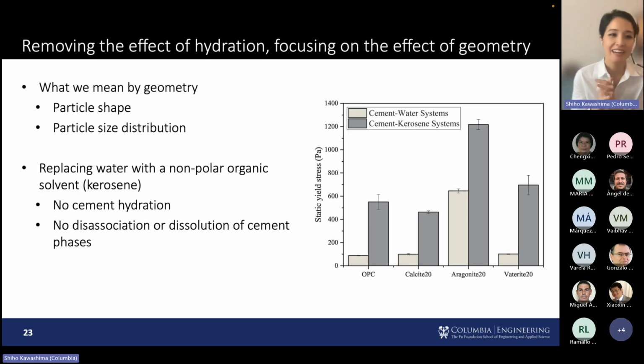And so to really isolate this effect and remove the effect of hydration, because I'm so sad to have missed Nicholas' talk, but I'm sure Professor Roussel emphasized that, the progression of hydration, even though we are in the dormant period or the induction period, it will have an impact on your fresh state properties, on rheology. So we want to eliminate that, and we did that by replacing water, which is critical for the hydration reaction, with a nonpolar organic solvent, kerosene. And so by replacing water with kerosene, we eliminate cement hydration. And also there's no dissociation or dissolution of the cement phases. So that means there's no charging effects either.